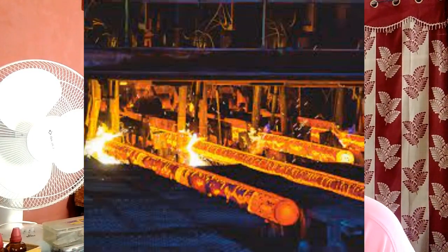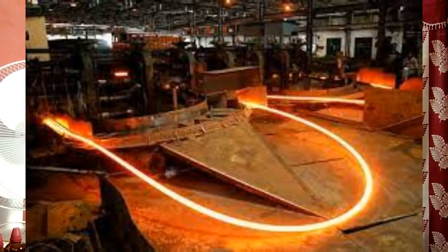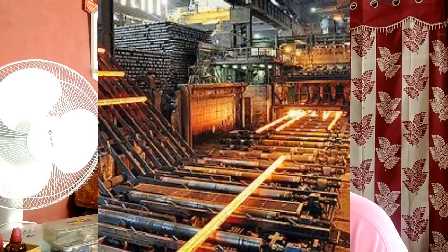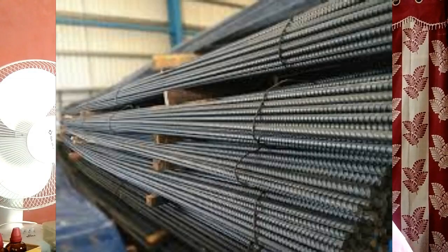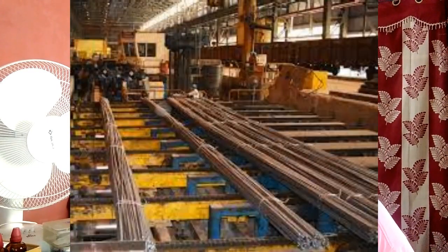Under thermomechanical treatment of bars, the steel bars are made to pass through a specially designed water cooling system. These are kept for such a period that the outer surface of the bars becomes colder while the core remains hot. This creates a temperature gradient in the bars. When the bars come out of the cooling system, the heat flows from the core to the outer surface. It causes further tempering of the steel bars, thereby helping them attain higher yield strength. TMT steel bar is a newer variety of steel for construction purposes.